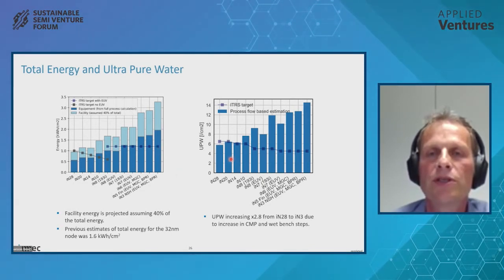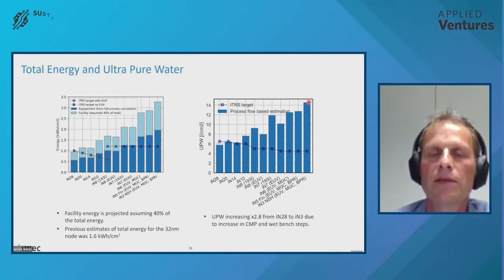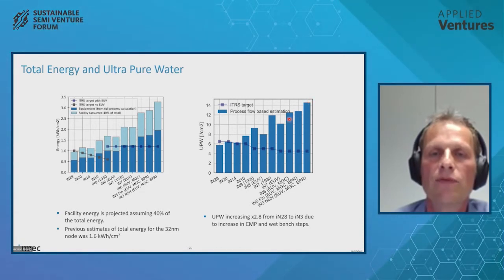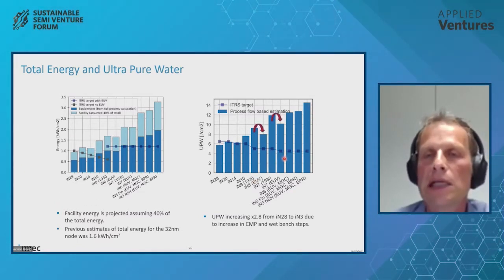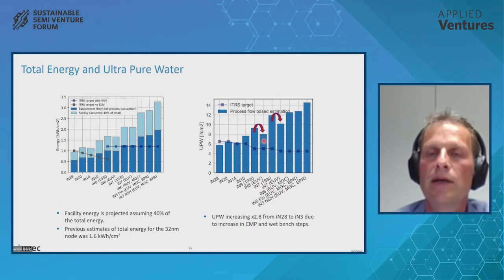Furthermore, the water usage is also increasing quite a bit. We see going from 6 liters per square centimeter up to more than double of that, 14 liters per square centimeter, because of all the different steps that need cleaning, etc., in the more advanced nodes. Again, here, EUV shows up to be improving the water usage simply because we use fewer steps.